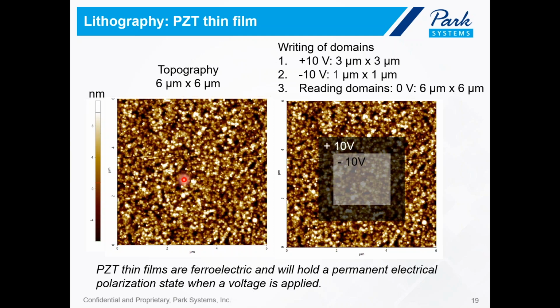So what we will do is that we will write a domain of 3 microns by 3 microns. To do this, we simply choose a 3 micron by 3 micron scan in the AFM, and then we scan it with the applied positive 10 volt DC bias to the tip.